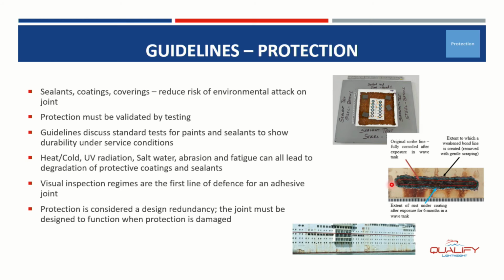You can do the same sort of thing with a laminate, in that we can put some kind of damage into the laminate, expose it to conditioning, and then examine the interface afterwards to see if there's been any rusting under the laminate, or any decrease in the bond strength. And that can give us a good idea. There's some anecdotal evidence that there's rust creeping under composites to steel joints, and it's important to understand for your particular set of systems, for your resin system and the steel preparation that you use, that that's not going to be the case.